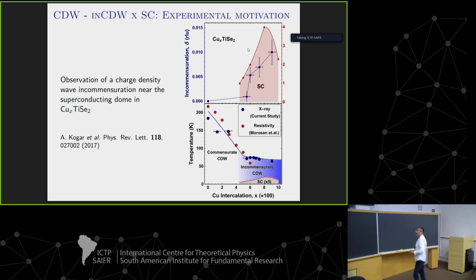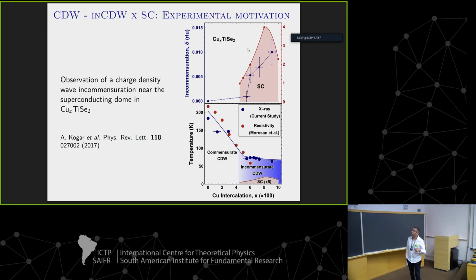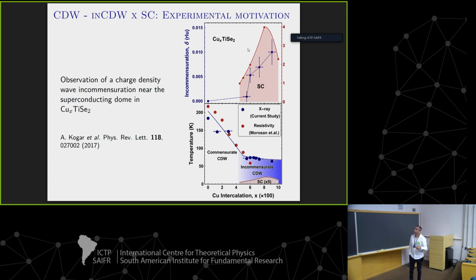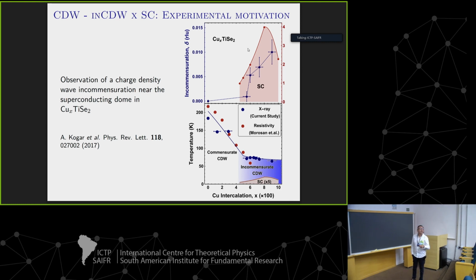Later on, even for the same compound, in 2017, this phase diagram was reported. Again, it is temperature as a function of copper intercalation. And again, we see for high temperatures a commensurate charge density wave, but at low temperature, we see an incommensurate charge density wave emerging near the superconducting dome.